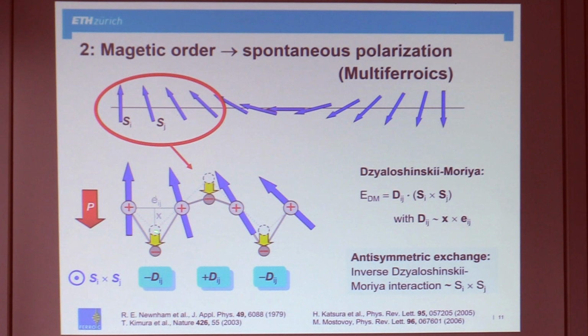Now you see that those that are displaced towards the lower part, here you get a negative energy contribution because x is negative. So in order to have the lowest possible energy, x becomes larger, or rather more negative. Then this energy contribution becomes more negative, and that is achieved by moving these ions down. Here you have a positive contribution to the Dzyaloshinskii-Moriya energy term because x is positive. So x is made less positive. Again, the ions shift down. So in total, all the intermediate ions shift down, and then you get a resulting polarization. That's how this magnetically induced polarization comes about.